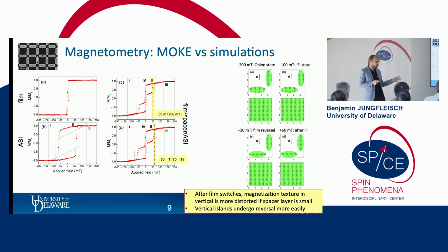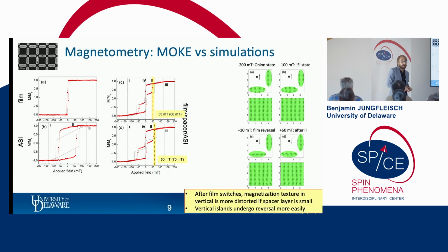Now, what we observe here by looking at the different spacer layer thicknesses is that after the film switches, the magnetization texture in the vertical elements is more distorted, and this leads to a situation where the vertical elements undergo reversal more easily, and this explains the lower switching field for the thinner spacer layer. You can also see that we always systematically overestimate the switching field in the micromagnetic simulations compared to the experimental results. And this is due to the fact that we have a distribution of shapes in the experiment which result in this more smooth and gradual change of the magnetization.